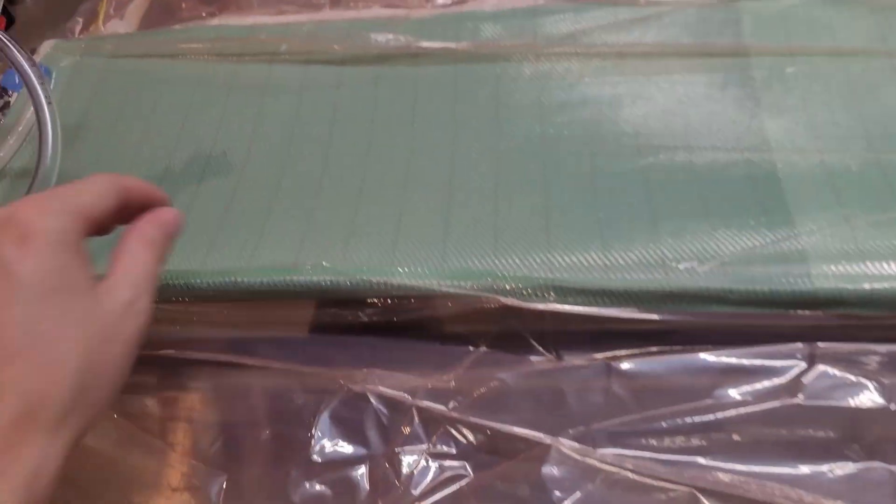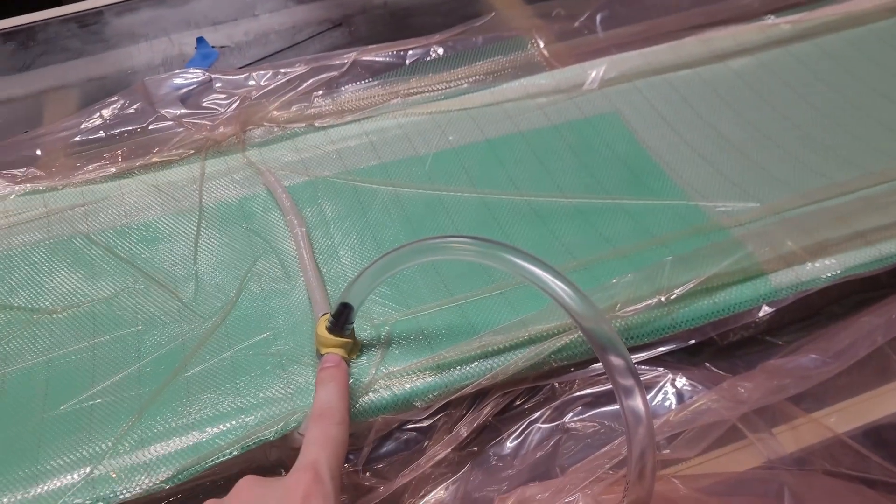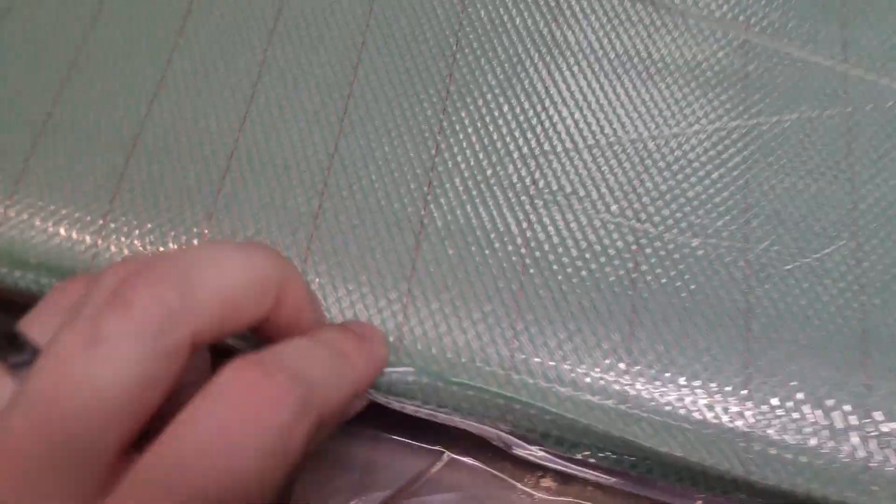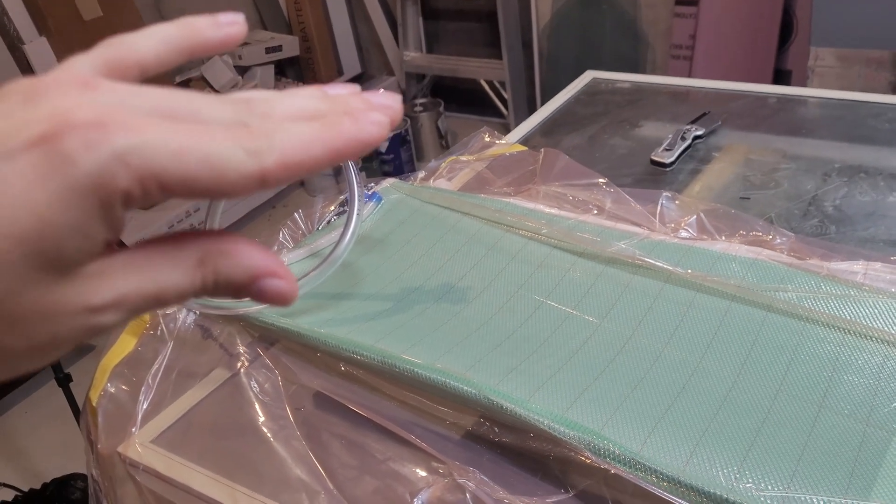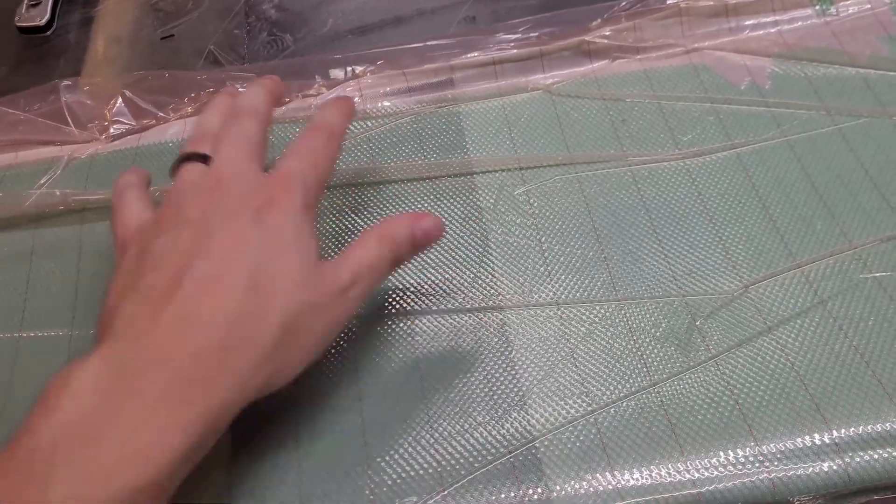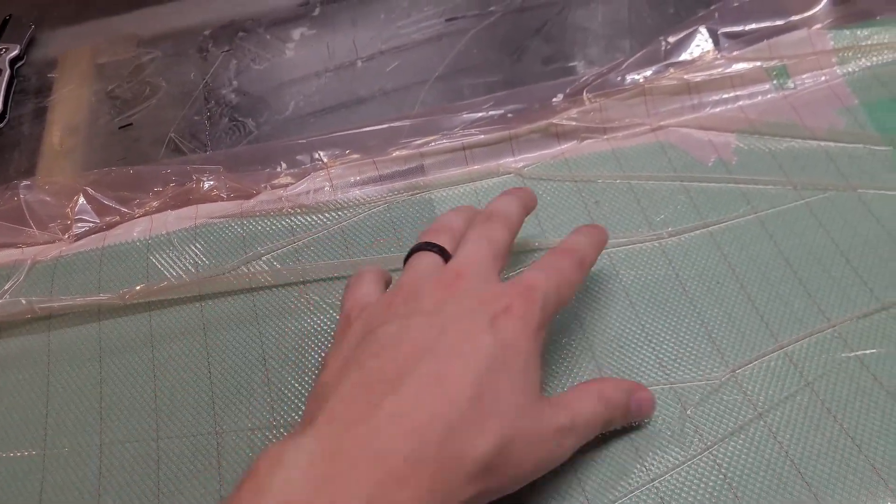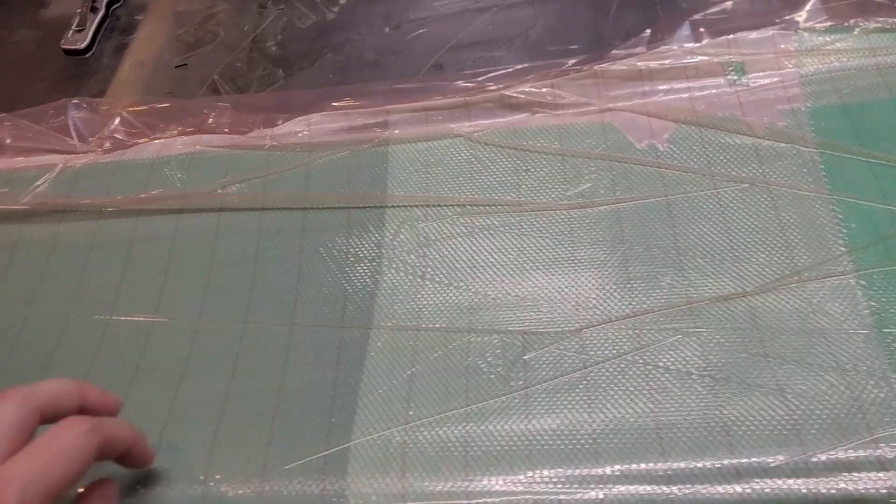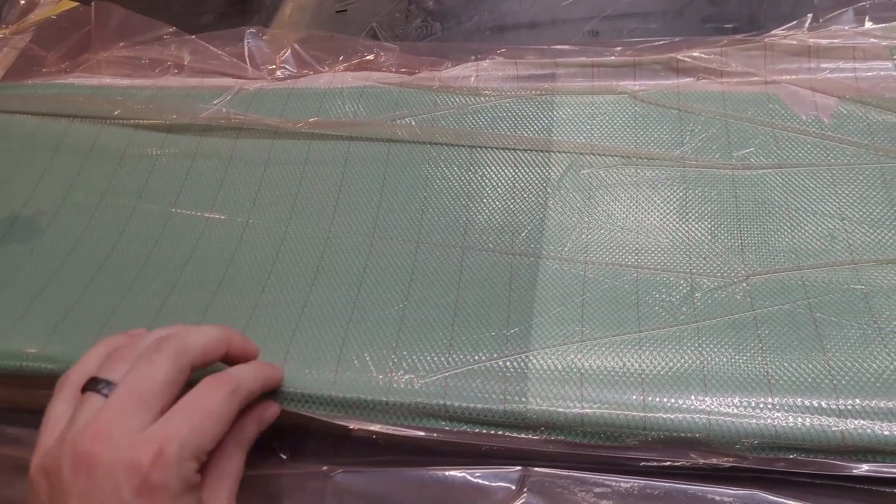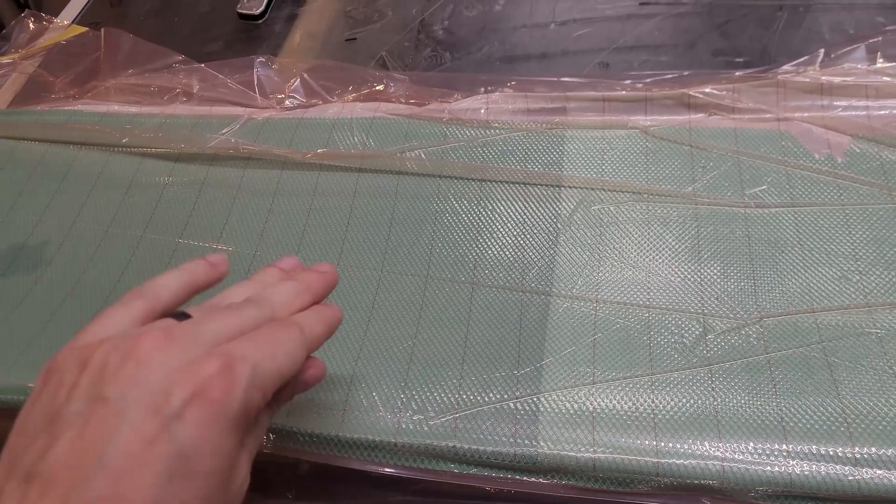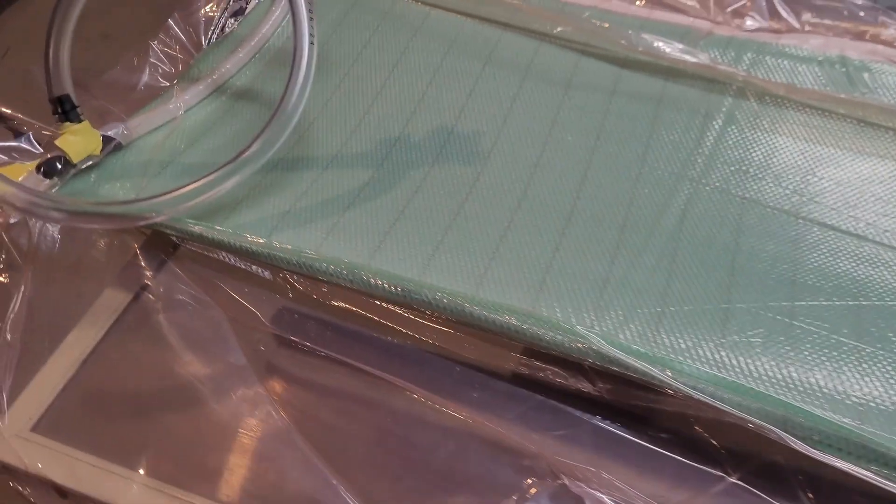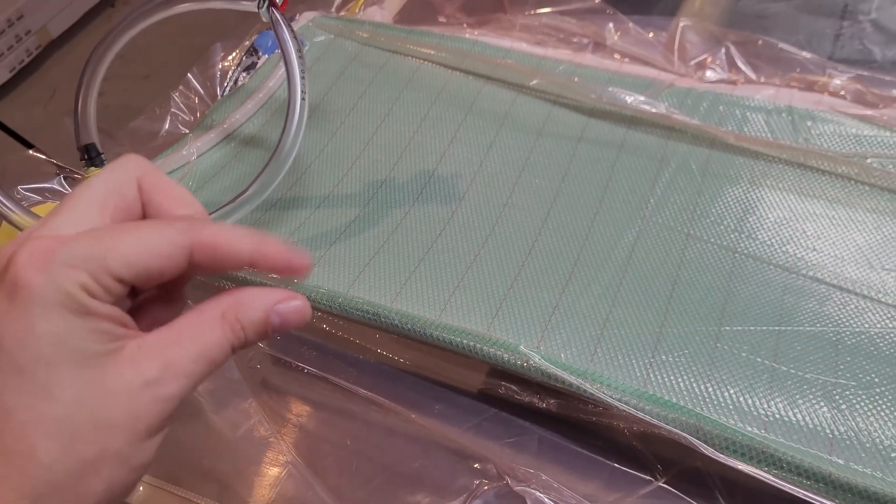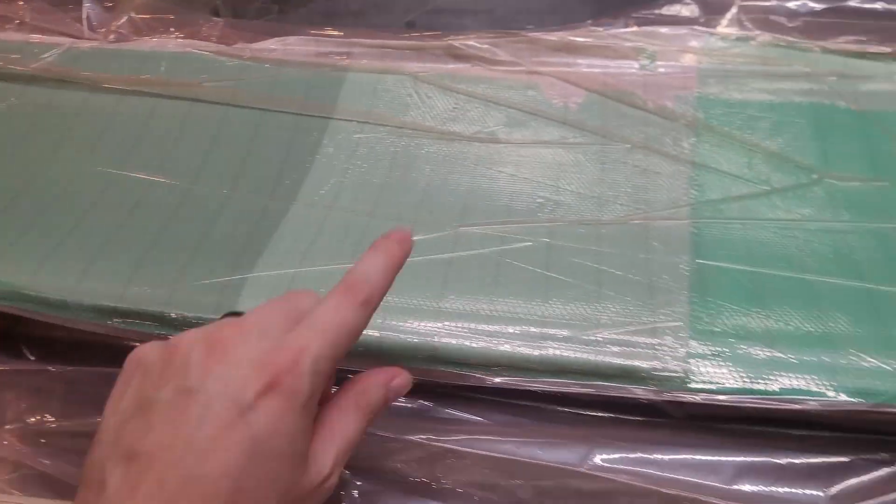Alright. So we have it all bagged down. I got my inlets for my resin on either end and my vacuum port in the middle. It's kind of bunching at this front edge, and I'm kind of worried that it's grabbing that front edge carbon and pulling it out. But at this point, I can't get it to actually pull this way anymore because the resin matrix is very kind of pokey. So it's grabbing the peel ply and pulling with it because this isn't following the front leading edge. It's just kind of crushing because the bag is going to squeeze both ways. So there might be a little bunch of carbon at the front edge. So I might have to trim that off and patch it later.